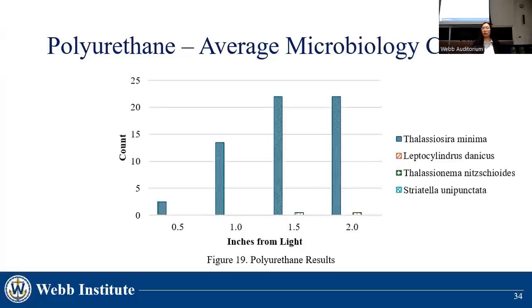Thalassiosira minima, shown in blue, was extremely abundant on one of our 2 polyurethane plates. Note that the y-axis is adjusted to accommodate this concentration. A clear reduction in growth towards the center of the plate can be seen, as expected. No other microbiology types were recognized for this plate, performing better than the bare or epoxy tests by variety. However, the count of Thalassiosira minima far exceeds that seen in any other test case.